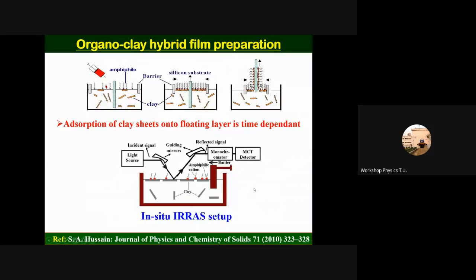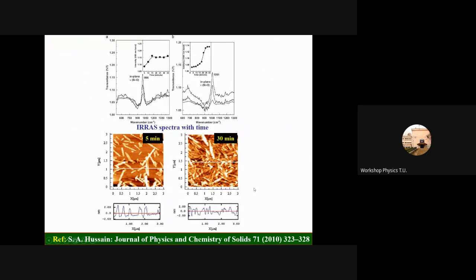And if we plot the intensity of the vibration of the SiO bond, then you can see here that initially the intensity was very low, and with time the intensity increases, and after some time it flattens. That means almost all the dyes are attached to your clay.